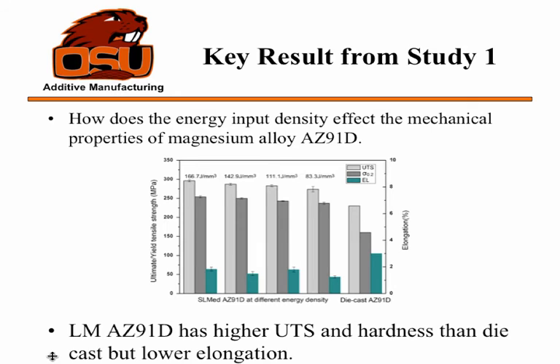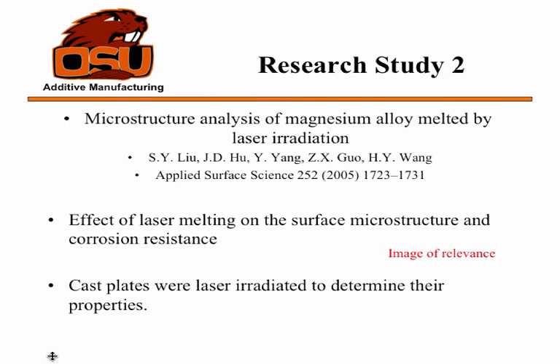So you can see that all of the properties as far as strength go are higher, but the elongation is lower. That's because it's a harder material because of higher cooling rates than you can achieve in die casting. So it has a much higher, more eutectic microstructure, which we'll talk more about in this next study.